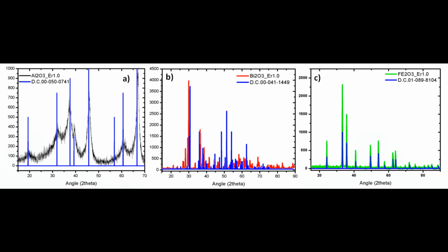In the diffractograms, we can see that for the aluminum oxide, a hexagonal phase was obtained with a small crystal size associated with the tightness of peaks. On the other hand, the bismuth oxide and iron oxide samples present a high purity and crystallinity in the monoclinic and rhombohedral phase respectively, with low symmetry which helps to produce a better luminescent response, where the presence of the erbium ion does not significantly modify the crystalline structure.